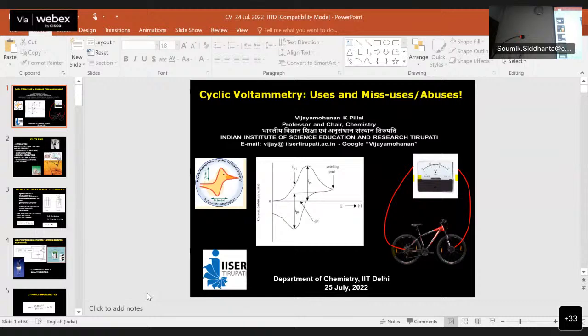In some research articles, they put AgCl in all media. That is not correct. If you are doing chloride media, AgCl and calomel can be used. If you are using sulfuric acid and you put chloride, what happens? Cl minus will go into the solution. So the Cl concentration keeps on changing because from AgCl, you have some chloride. Slowly chloride will diffuse into the system and it will contaminate and change things. And also this is a time dependent phenomenon. That is the reason why we say don't use AgCl in sulfuric acid.